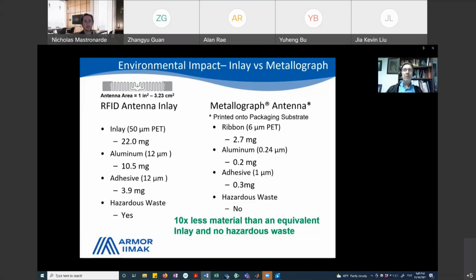Aluminum is not a sustainable material as it's mined, and vast amounts of electricity are required to convert aluminum oxide to aluminum metal, creating a big carbon footprint for this metal. So a 50x reduction in aluminum usage greatly improves the sustainability of the thermally printed tag. Many people point out that the spent ribbon waste has to be considered, and indeed it does. However, the PET film used for the ribbons is 8 times thinner than the PET film used in the inlay.